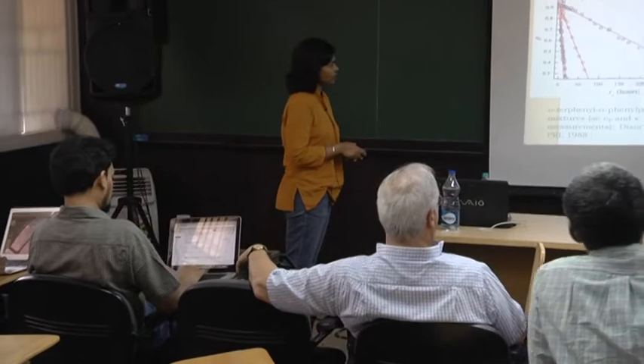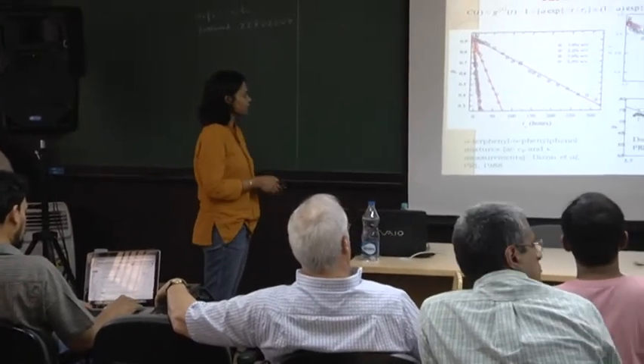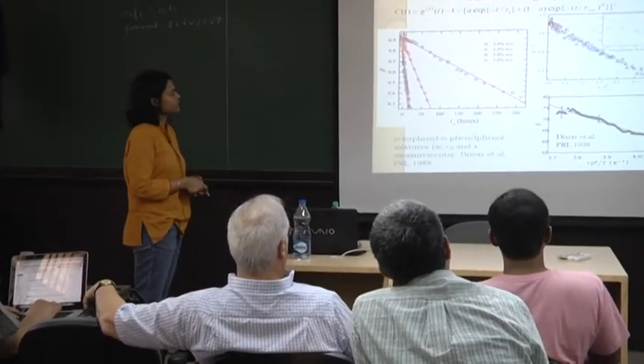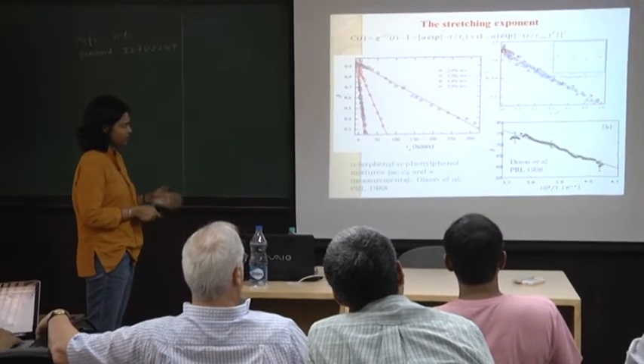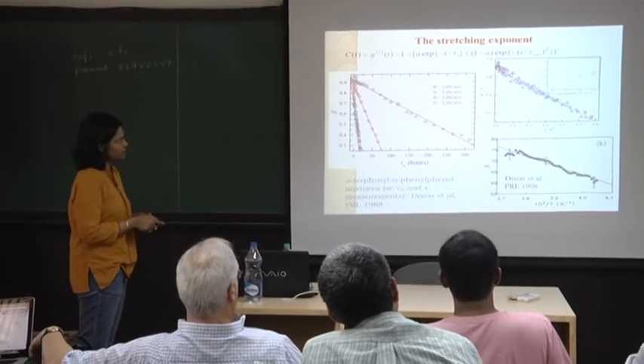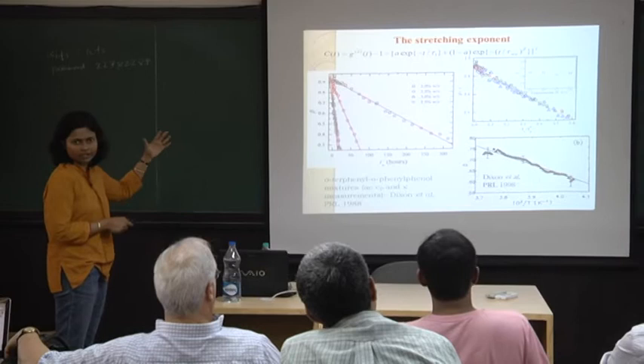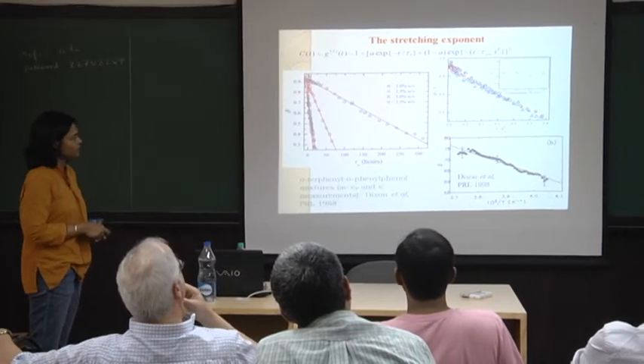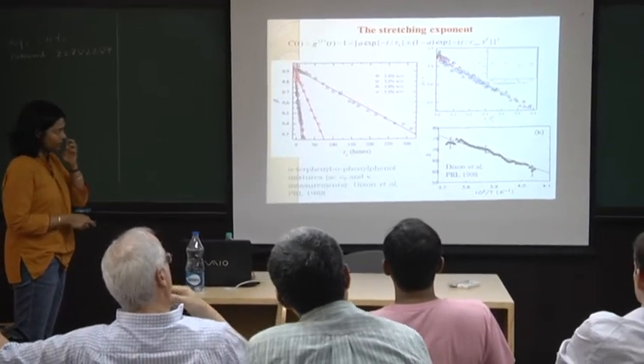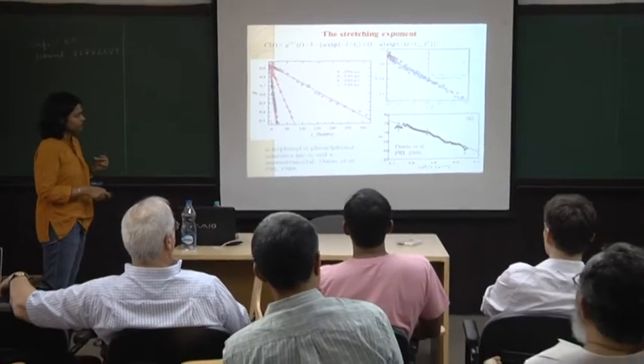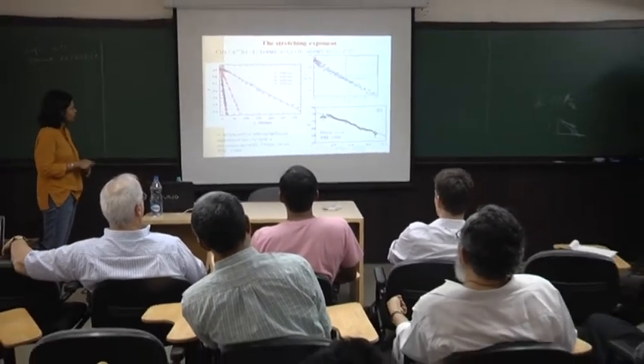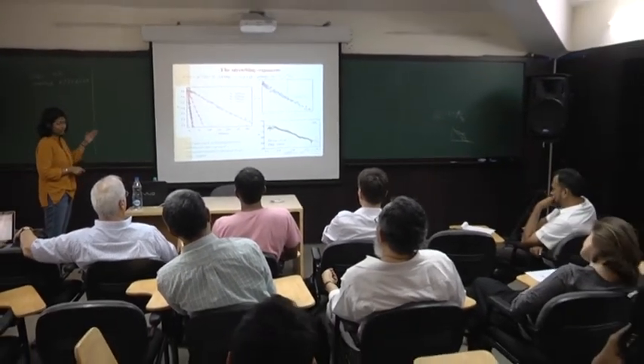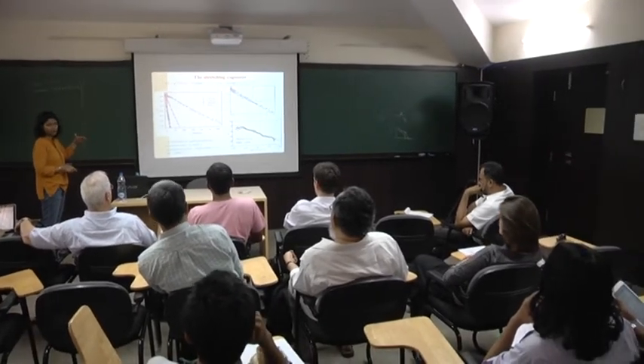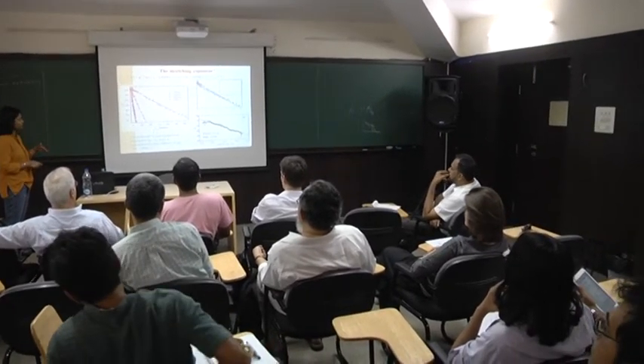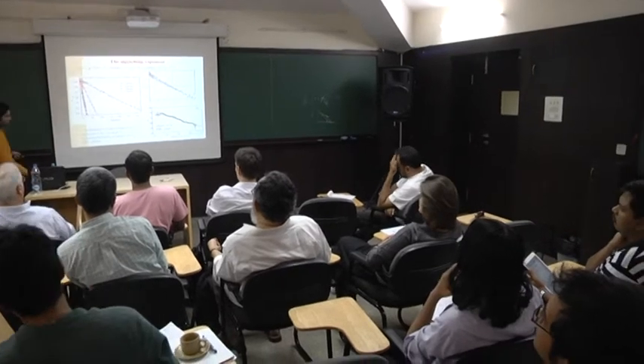Here you have a mixture of two organic liquids. These were some specific heat and thermal conductivity data that were taken. And here again is the stretching exponent. They used a similar kind of functional form to fit the data. You find that even in their case, beta decreases linearly with 1 over temperature. We see something very similar. Here, of course, our parameter is not 1 over temperature, it is the age of the system.